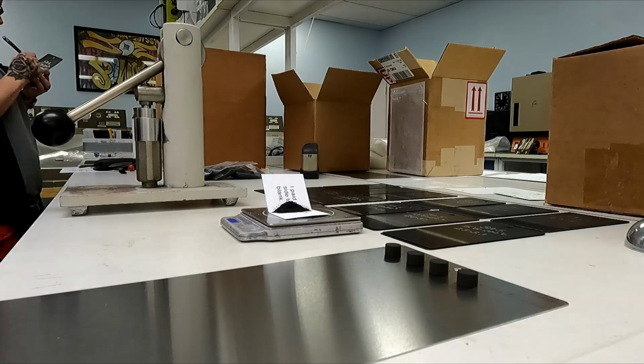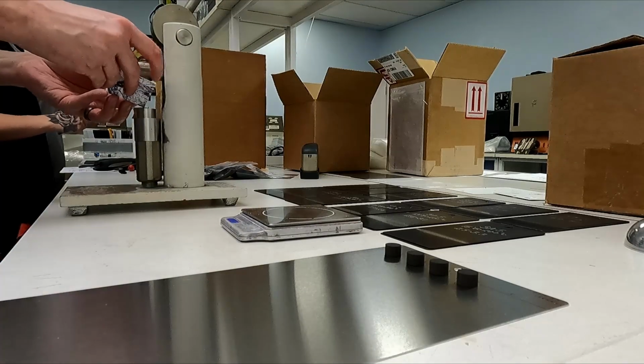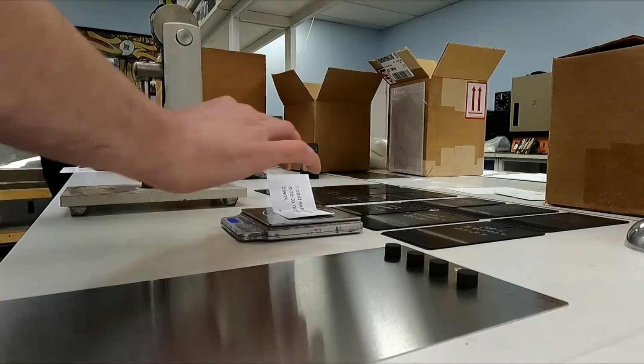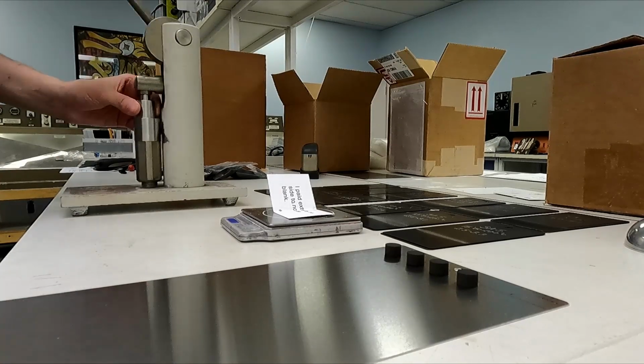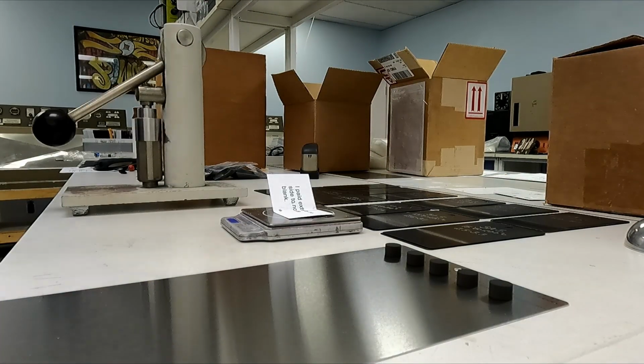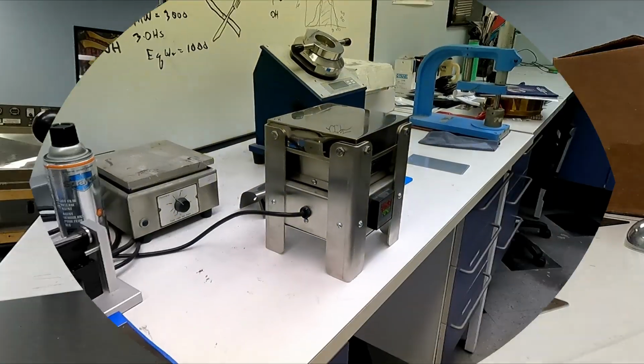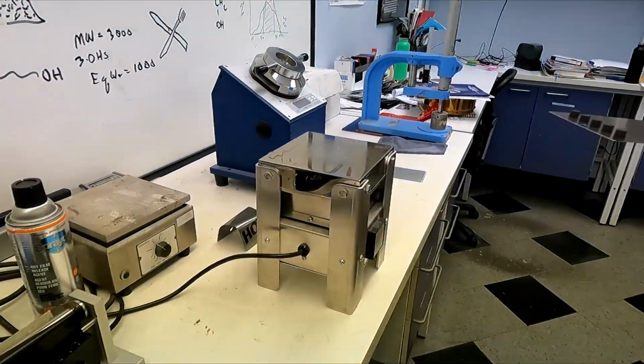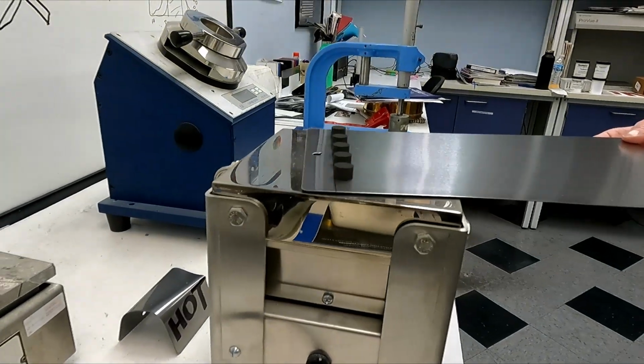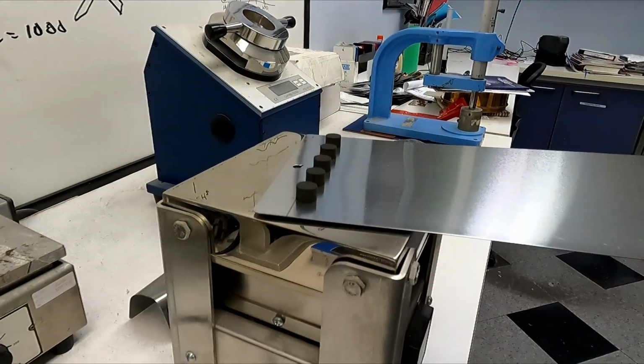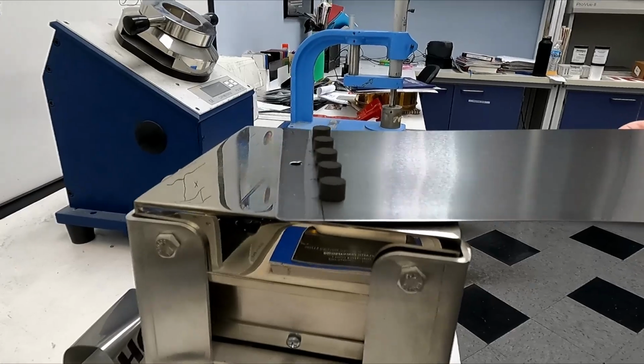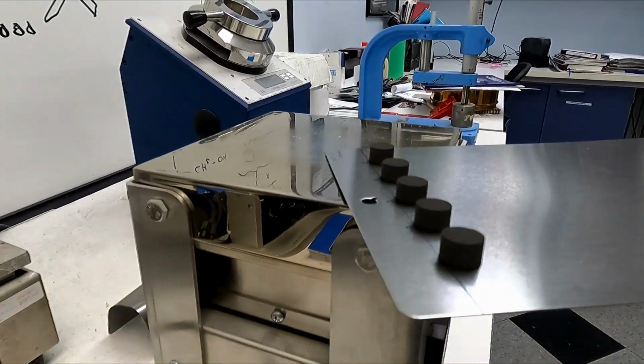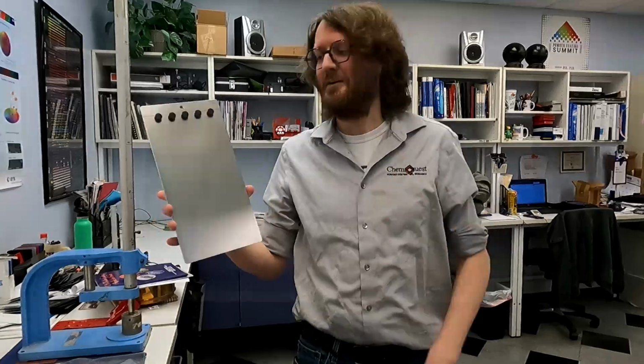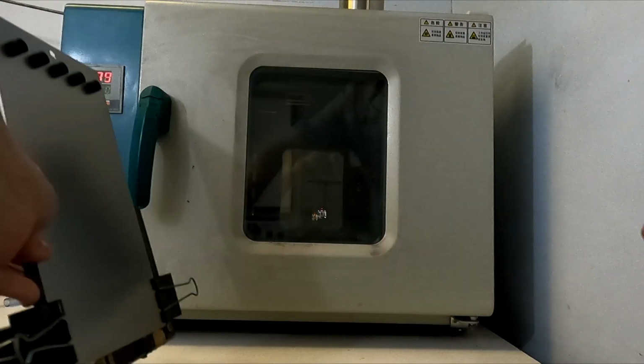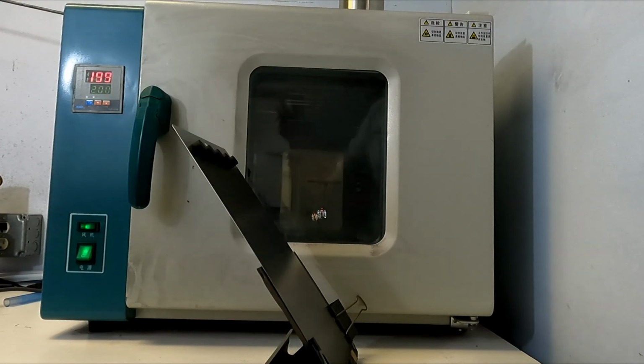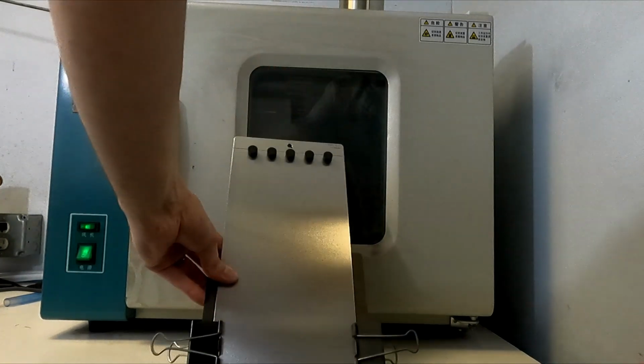As the thermosetting cure reaction takes place, viscosity rises until the flowed powder fully cures and becomes solid again. If the flowed pellets were different batches of the same material, and especially if they were compared to a control which is known to be a good sample, you should expect the length of the flows to be very similar. If they are not, this could indicate a potential issue with one or more of the samples. On the other hand, if you're comparing a series of different powders, say for example you're trying to choose a new filler or extender pigment and have incorporated a half dozen different types into the same base formulation, differences in the results can give insight into which filler is best for your needs.